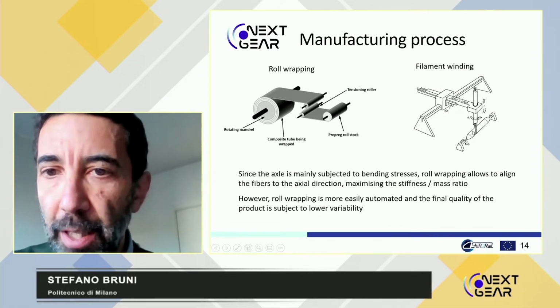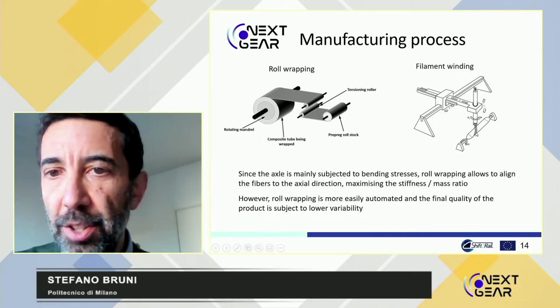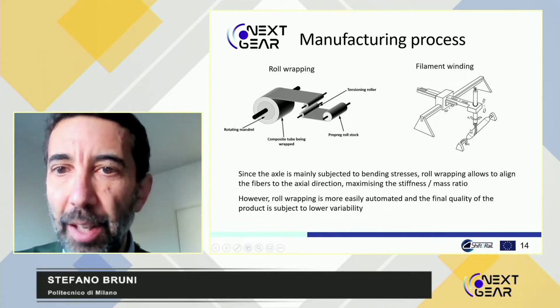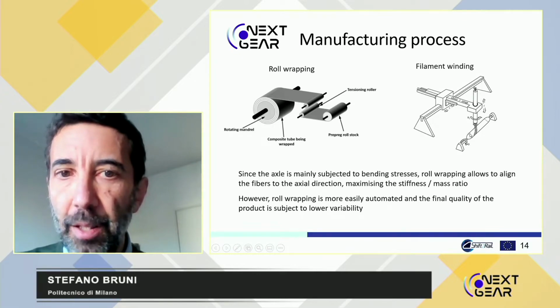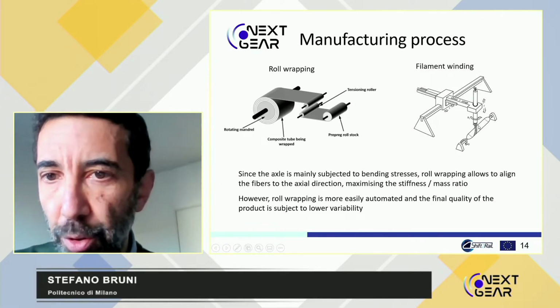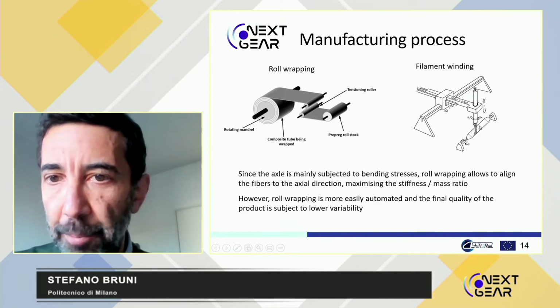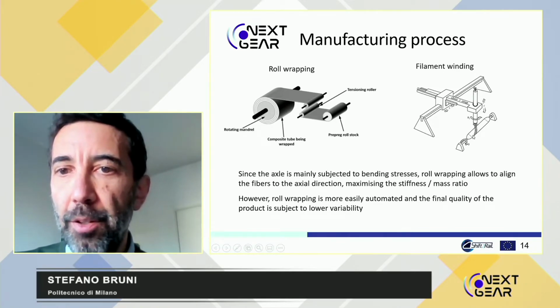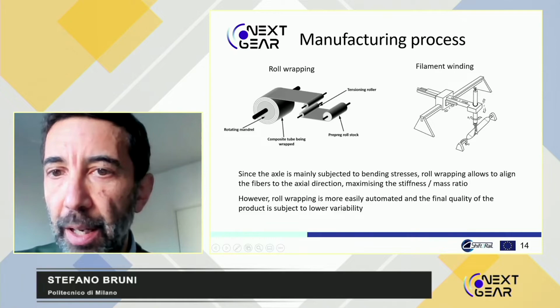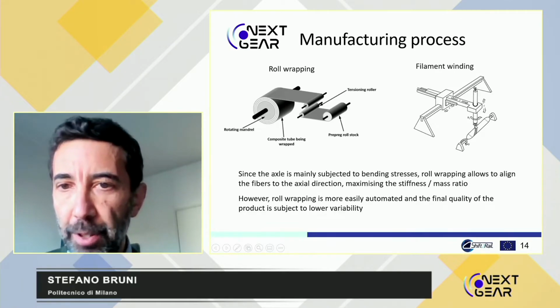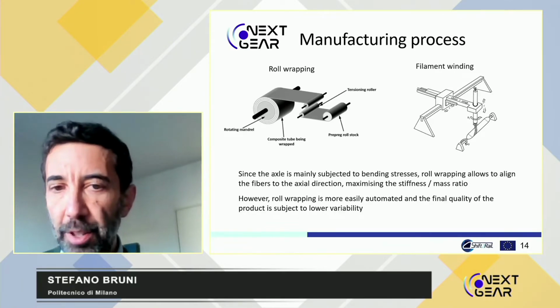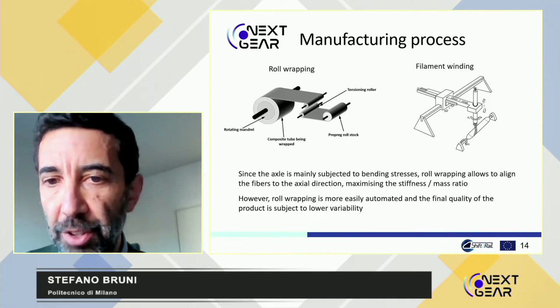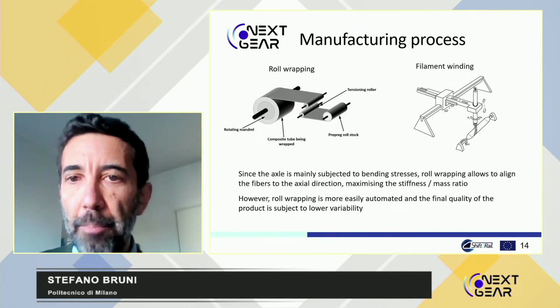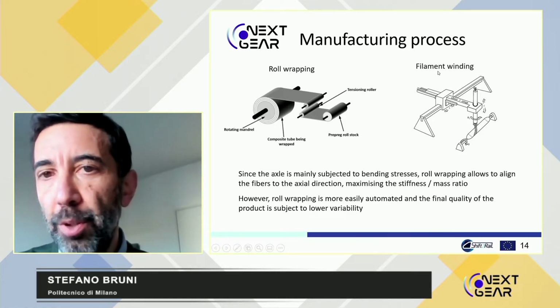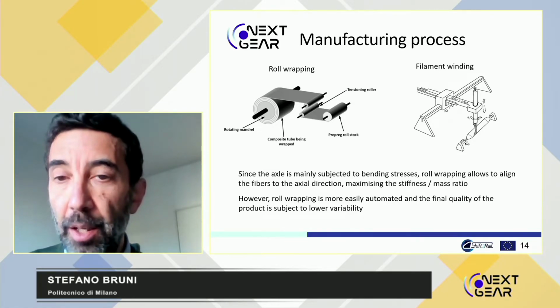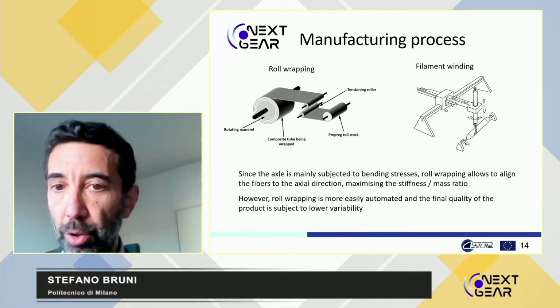In filament winding, as you see from this sketch, it is clear that you cannot directly align the fibers axially, because then you could not wrap them around the mandrel. So you need to have some kind of angle for the wrapping, and this leads to a slightly reduced ratio of stiffness versus mass. But the nice point with filament winding is that this is a process that can be made totally automatic.